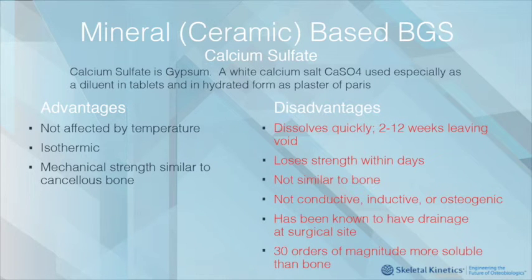The disadvantages are it dissolves very, very quickly in 2 to 12 weeks, leaving a void. It loses strength within days, thus it could compromise your fixation. It is not similar to bone. It is not conductive, inductive, or osteogenic. It has been known to have drainage at the surgical site, resulting in extra care for the patient. And it is 30 orders of magnitude more soluble than bone.